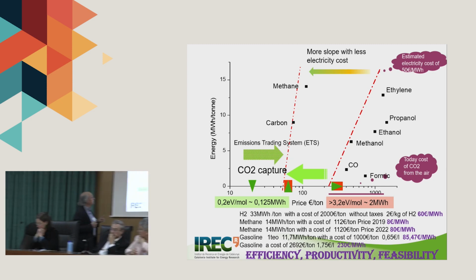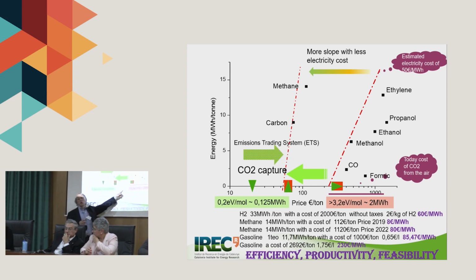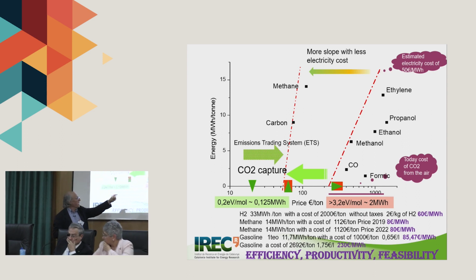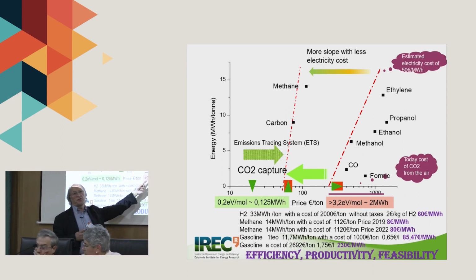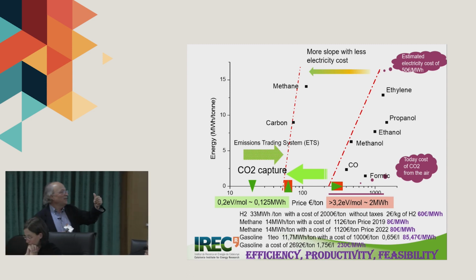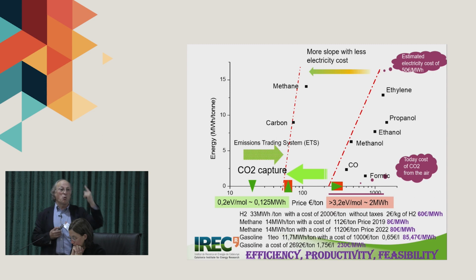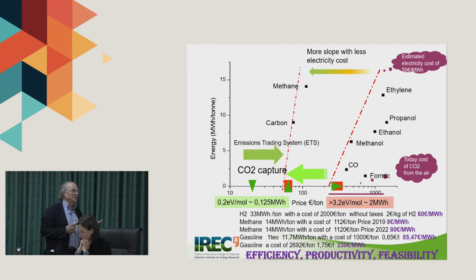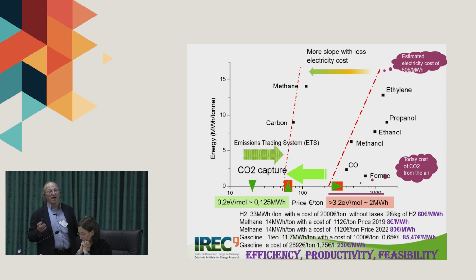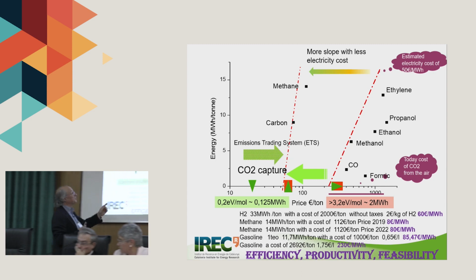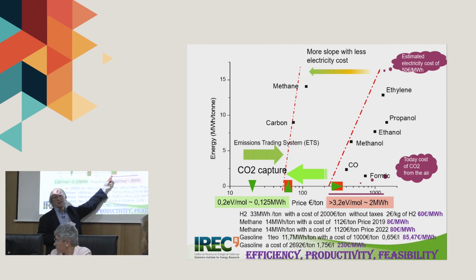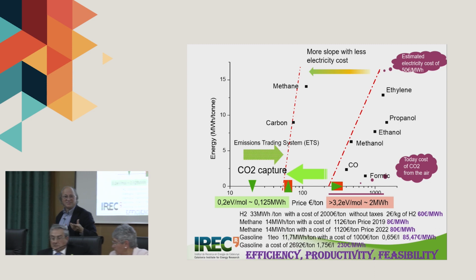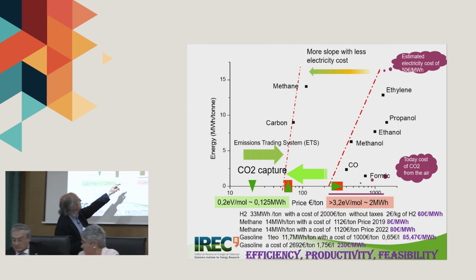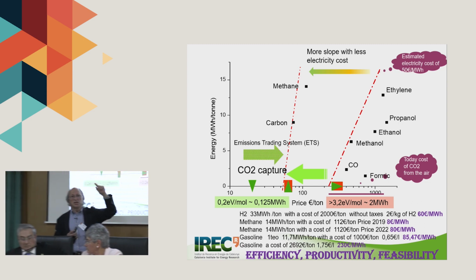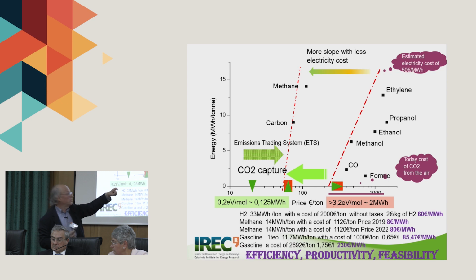Observe, capture, the price of the ton of CO2. Today, the technology is using more than 3 electron volts per molecule. This means that for 1 ton you need 2 megawatt hours of energy. What is the price of the megawatt hour of energy? So this is the reason that, for example, direct capture from air is 300, 400 euros per ton. This is quite expensive. And then you need the energy that you need for the process, this red line. So this is the final cost.